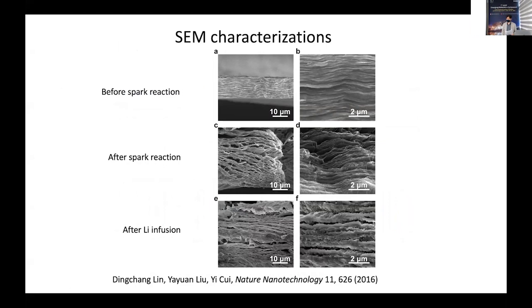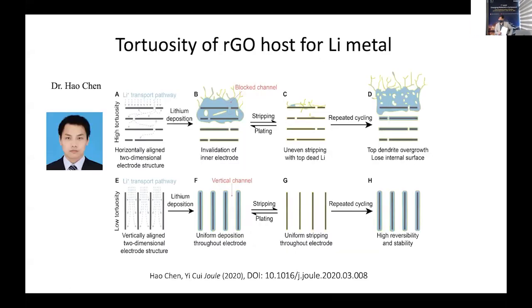Then we further ask the question: you can have horizontal graphene oxide, what about if we align the graphene oxide vertically? What will be the difference? Because lithium needs to transport through this graphene oxide and deposit inside. If you have vertical alignment, your tortuosity will be 1. If you have horizontal alignment, your tortuosity will be high. So vertical tortuosity will reduce the ionic resistance, the bottom row right there, and the plating of lithium metal onto this graphene oxide back and forth will be more uniform. We think the bottom will be better.